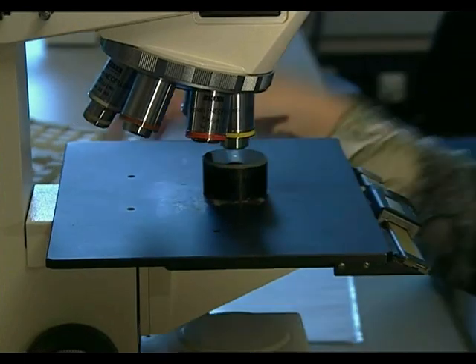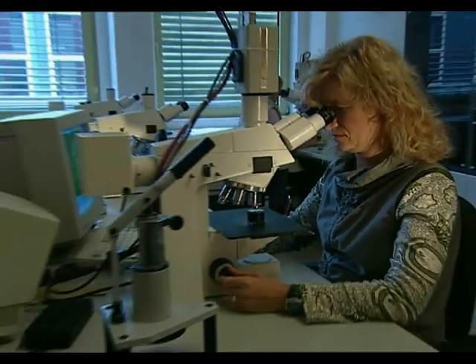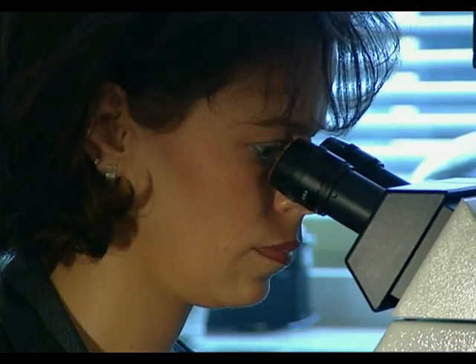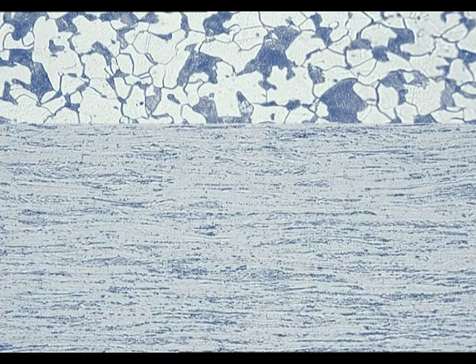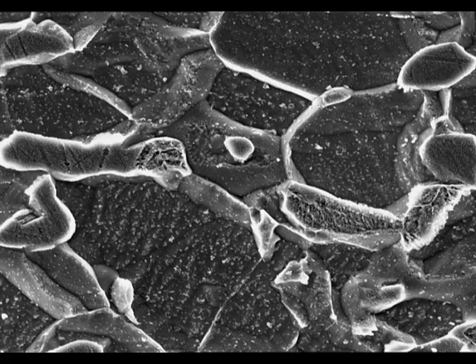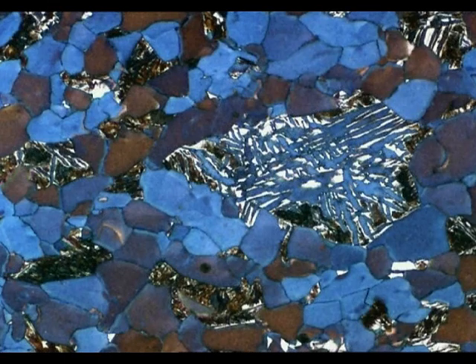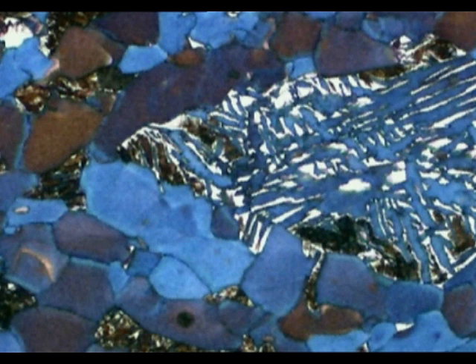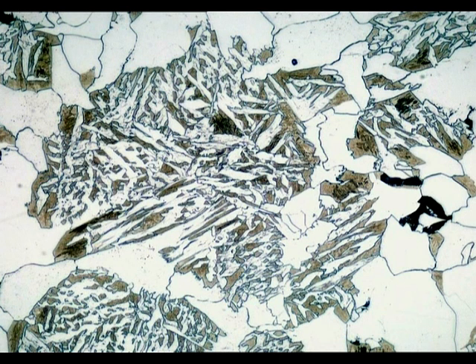The reason for multiple hot and cold rolling can be seen under the microscope. Steel has a crystalline microstructure; the individual crystals are known as grains. In hot rolled steel, the grains are still relatively large. They are stretched to an extreme degree during cold rolling. Subsequent annealing gives rise to new grains, whose nature, size and distribution can be exactly controlled. Multi-phase steels are one example of this — the white and brown areas are especially strong, while the blue particles are soft. Thus, the steel is both strong and formable. A suitable steel can be produced for every application by influencing the microstructure.